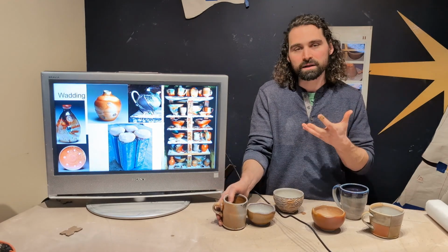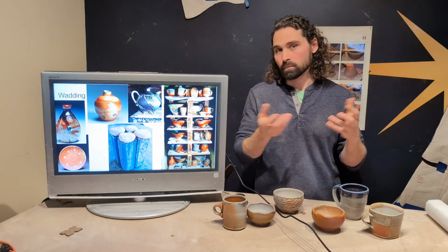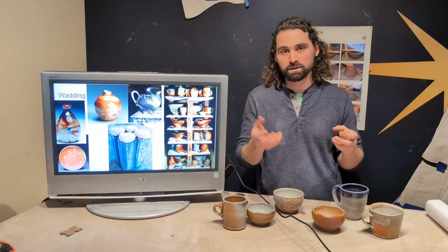The wadding, what it is, is usually a refractory material, in most cases alumina hydrate, mixed with clay. Often like a ball clay, fire clay, kaolin, something that is mixed together to create the wadding. It's pretty much a kiln wash recipe, but mixed as a clay body.